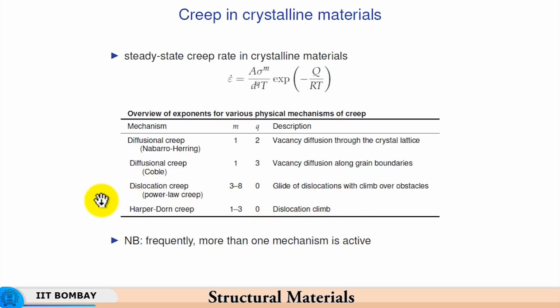So, these are dislocation based motions, or dislocation based creep deformation, and at any given point of time you can have more than one mechanism active. For example, at high temperatures you can have a very small amount of, say, dislocation based creep. Most of it will be dominated by vacancy diffusion through the crystal lattice, but still you can have a very small amount of dislocation activity. So, as the temperature increases, the proportion of dislocation activity decreases, and the proportion of diffusion related creep increases, or diffusion related mechanisms go on being dominant. So, these mechanisms dominate at high temperatures.